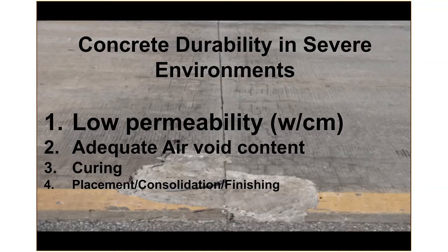By not keeping the water in there and keeping the Portland cement happy and hydrating and producing the glues that hold the concrete together and making that surface dense and hard. If you don't accomplish that curing, you will see surface degradation up to surface scaling, but generally surface paste erosion, aggregates exposed much quicker than they should, aggregate polishing and things like that.